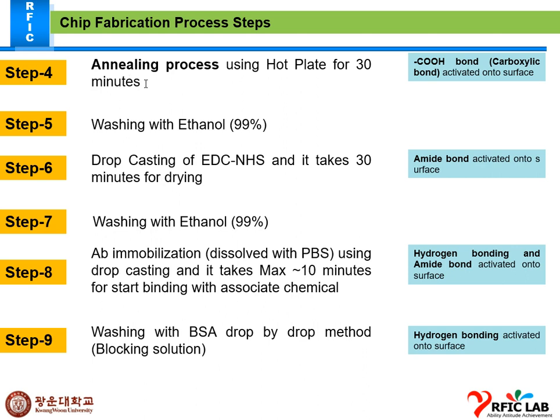So we have to put it on the hot plate at 80 degrees Celsius, so that the carboxylic bond is activated on the surface, and afterwards ethanol washing. Then drop cast EDC-NHS. It takes 30 minutes for drying, but then amide bond formation occurs, this is the antibody immobilization, and the hydrogen bond also forms on the surface to bind with the BSA, and then afterward BSA.